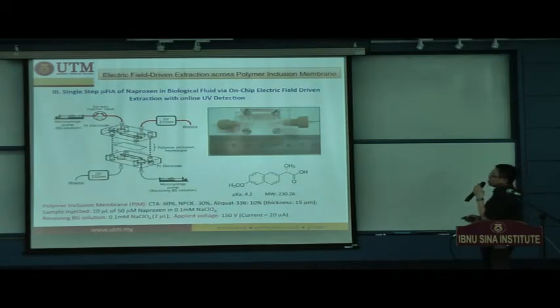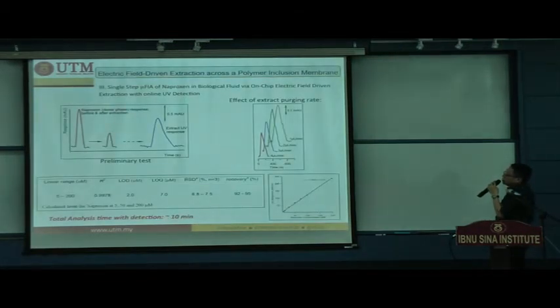For this example, we put 10 microliters of human urine sample that contains 50 micromolar of naproxen in the 0.1 millimolar sodium perchlorate background solution. The receiving solution here is only 2 microliters because this is a specially designed micro flow cell which only has 2 microliter volume, and the applied voltage is only 150 volts during the extractions. So this is the result that I'm showing first.